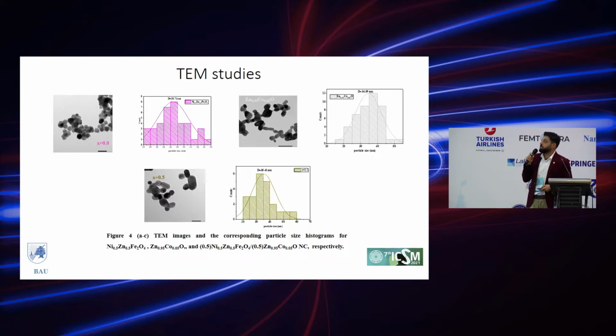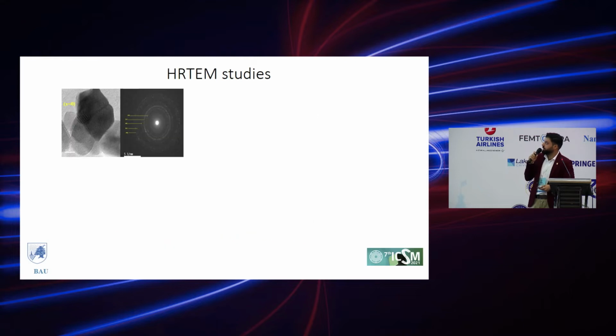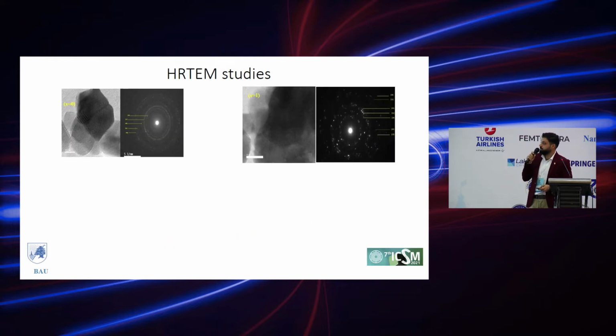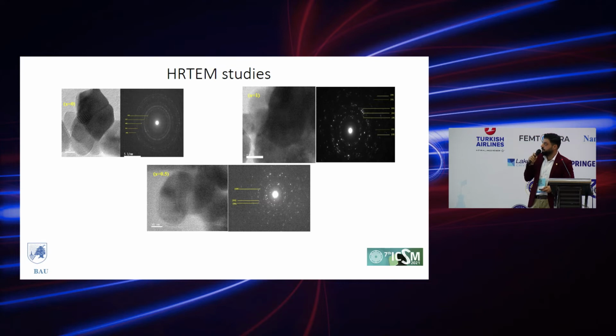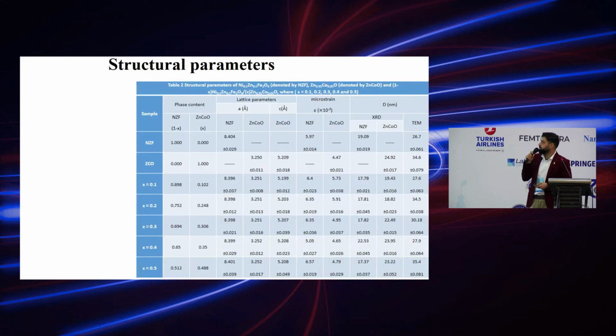The transmission electron microscopic studies have confirmed the synthesis at the nanoscale, and the grain size histograms have confirmed the synthesis of nanophase in the size range from 27 to 34 nanometers. The high-resolution transmission electron microscopic studies have shown different grains with different crystallographic plane orientations, assigned to the polycrystallinity of the samples, and the selected area electron diffraction patterns showed concentric circles from which the hkl indices were determined and were found compatible with those from the XRD studies.